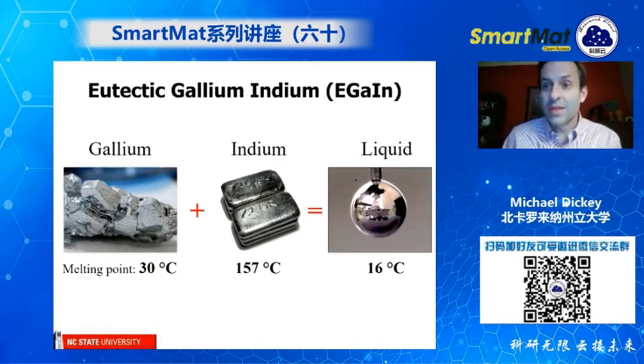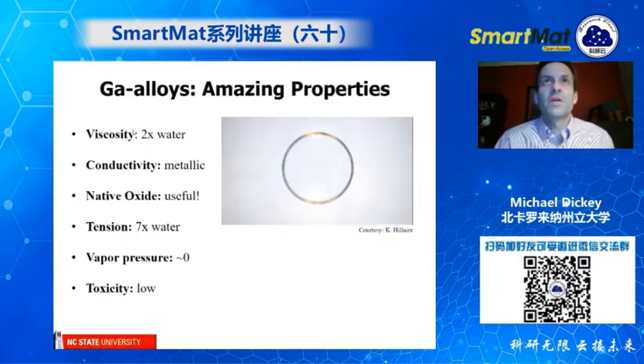So this material has a bunch of interesting properties, and I'm going to tell you about it. I'm biased, but I think it's one of the most interesting materials on the periodic table. So first of all, its viscosity is like water. It's literally twice that of water. The conductivity, both the thermal and the electrical conductivity, is metallic. The surface forms a native oxide. I'm going to be talking a lot about that today, so make sure you pay attention to this. The surface tension is the largest of any liquid at room temperature. It's about 7 times that of water, or maybe even 8 times. It's huge. The vapor pressure is about 0, so that means you don't have to worry about breathing it.